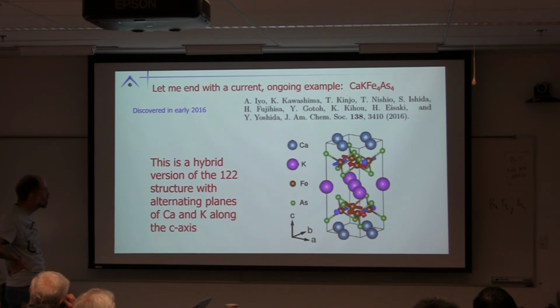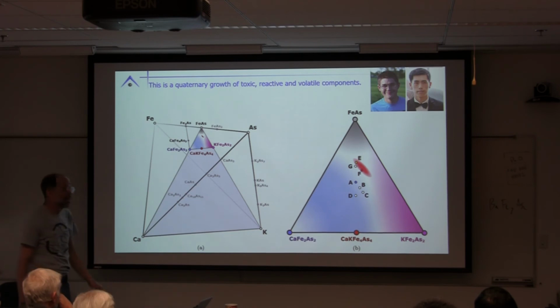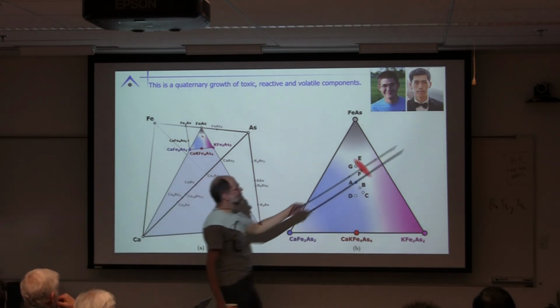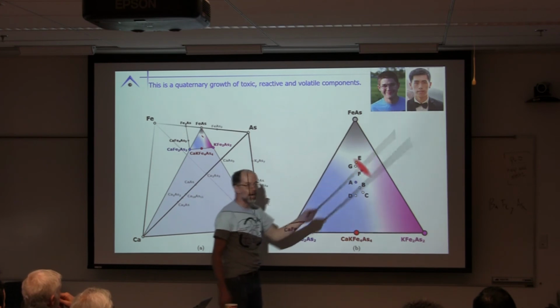Okay? This is a true quaternary that superconducts at 35 Kelvin in the pure form. No disorder, not doped. Okay? So we really wanted this compound. Okay? So we're back to the beginning. Okay? Now, this compound is not easy. This is a quaternary. A quaternary phase diagram, just compositionally, is a tetrahedron. If you want to add temperature, yeah, but it's just not pleasant. Good luck with that. But these two fine gentlemen, Ty and William, Ty is formal, William is not formal.